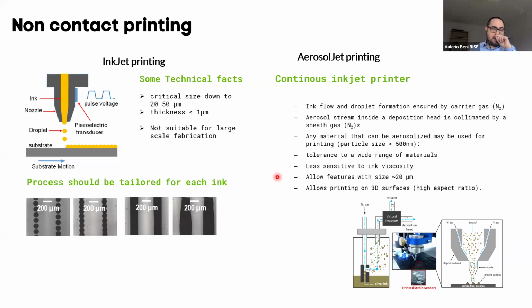A similar technology that is becoming more and more interesting, more and more attractive, is so-called aerosol jet printing. It uses a stream of gas to move the droplets, to generate the droplets. One of the advantages of aerosol jet printing compared with inkjet printing are two. The main advantage is that aerosol jet printing is more independent from the viscosity of the inks than inkjet printing. So in the case of inkjet printing, you really need to tune the viscosity very well, while you have a little bit more tolerance with aerosol jet printing.